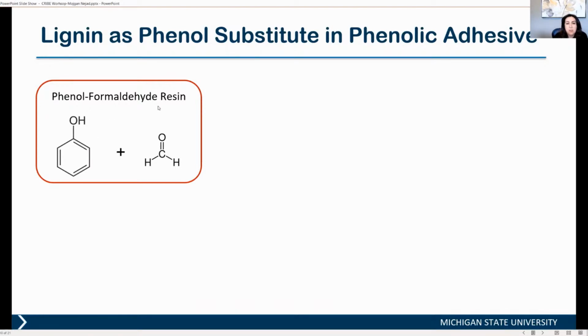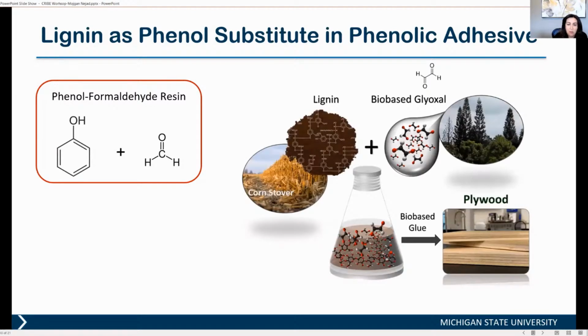Currently, the phenol formaldehyde adhesive or resin used for plywood and OSB manufacturing is made of phenol and formaldehyde. Both of them are made from petrochemicals, and formaldehyde is toxic. In the project that we work on and have filed a patent for, we replaced 100% of the petroleum-based phenol with lignin and 100% of the petroleum-based formaldehyde with glyoxal. Glyoxal is a bio-based dialdehyde produced from biomass or lipids, and then we mix them together. We were able to formulate a bio-based glue that could be used for plywood application. In this case, when we are using lignin and glyoxal, we can make a really good formulation for both interior and exterior application.